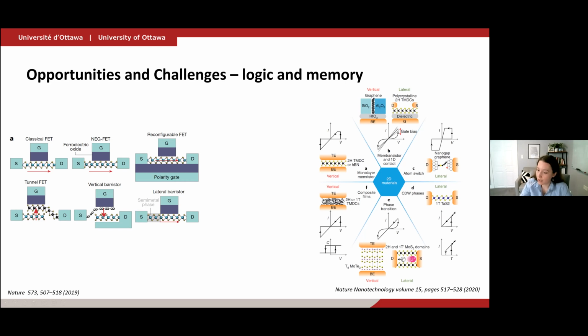Another example is intercalating lithium ions in between the layers, or taking advantage of the different coordination between the transition metal and the chalcogen, and having these 1T or 2H phases, as we call them, whether we have octahedral or otherwise coordination, and then you can apply an electric field and switch between the two structural phases, creating again a switch-like behavior in your device. So really a wealth of possibilities. And again, to emphasize, to make these into practical devices, we need to address a lot of material challenges. I'll come back to that a little bit towards the end of my talk.